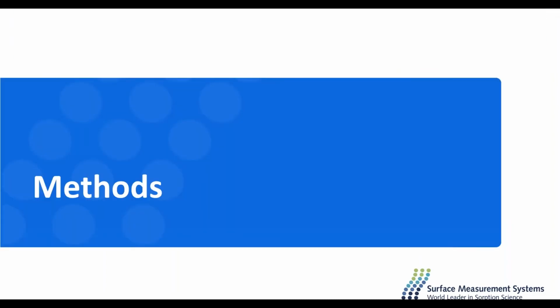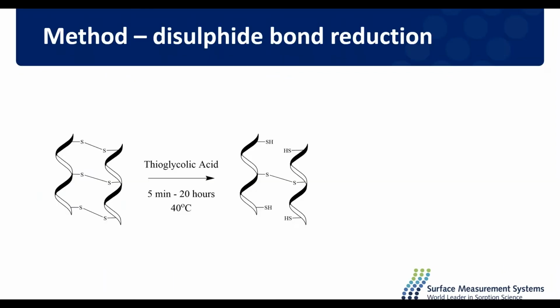So I'm going to talk a little bit now about the methods we used to reduce those disulfide bonds. The first method was using thioglycolic acid. This reducing agent is found in a lot of permanent waving solutions and relaxing treatments, and this reduces those disulfide bonds quite effectively. We performed this from 5 minutes to 20 hours so that we could get a range of hair samples with different crosslink densities. However, once disulfide bonds are reduced, they are known to reform over time.